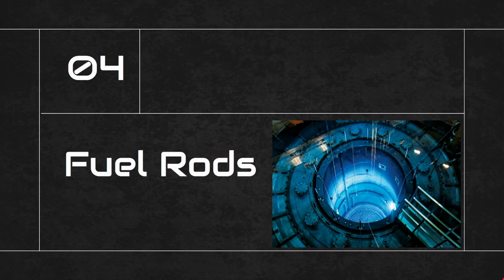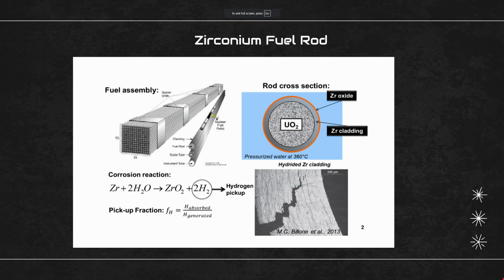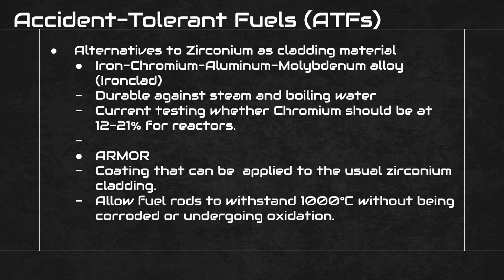Because of zirconium's reactivity in light water reactors, many researchers sought to replace or enhance the materials with other alloys and chemicals. One of these attempts at accident-tolerant fuels can be seen in General Electric's IronClad alloy, composed of iron, chromium, aluminum, and molybdenum. This alloy is able to endure steam and hot water reacting. At the moment, General Electric is still assessing whether the material should have 12 or 21% chromium for light water reactors.